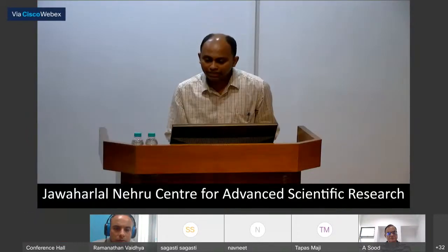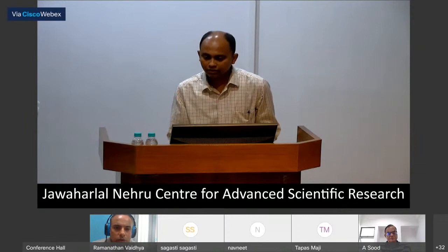So what is the typical crystallite size in these cases? Crystallite size of bulk material or nanomaterial? Nanomaterial. 2 to 7 nanometer. So that is the mean free path of the phonon size.